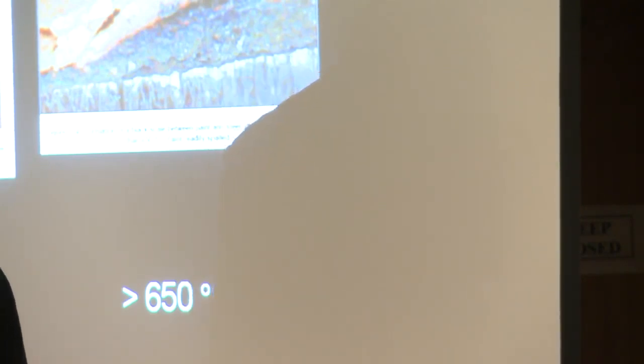Another argument depends on the thermal stability of the primer paint, because you may already think, why should somebody paint the World Trade Center with a paint which reacts violently at 650 degrees centigrade? Yes, that is true. And even in the NIST report, they used the thermal stability, or you may say reactivity, of the primer paint as a measure for the temperatures to which the steel beams had been exposed.